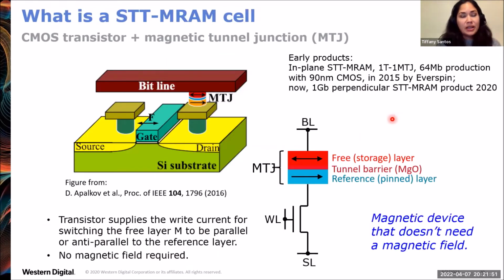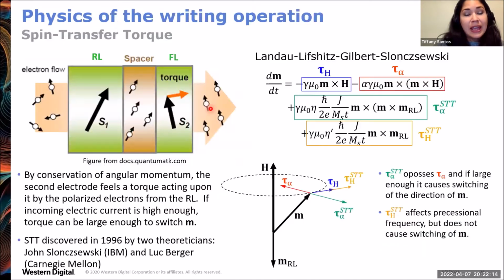So what is a spin transfer torque MRAM cell? It's this one magnetic tunnel junction that is your storage element and one transistor. The transistor supplies the write current to switch the free layer magnetization to be parallel or anti-parallel to the reference layer. And there's no magnetic field required here. So it's a magnetic device that does not need a magnetic field. And the writing happens by spin transfer torque.